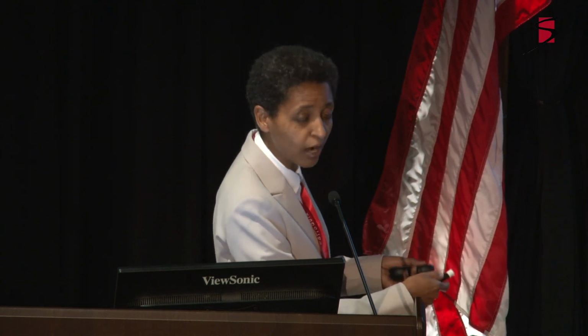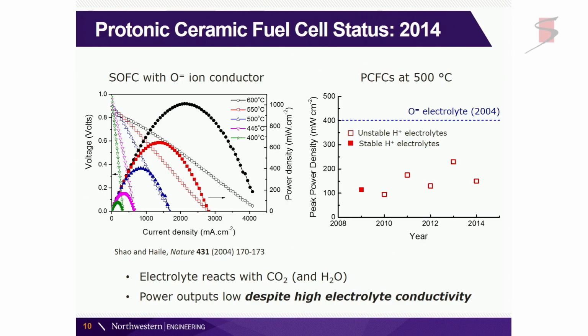Now, I showed you that the ionic conductivity of these proton-conducting electrolytes is quite high, so you might imagine that the fuel cell power outputs from these systems would be comparable to what has been shown for the oxygen-ion conducting systems. They're very similar in many ways. When we took a look in about 2014, when we got started with an ARPA-E project, at the time we were putting the proposal together, we said, look, this is really quite intriguing. If we look at the peak power densities from these fuel cell systems that use protonic ceramic electrolytes, they're nowhere close to what the oxygen-ion conducting system had done 10 years ago.